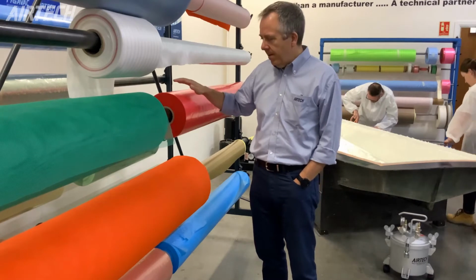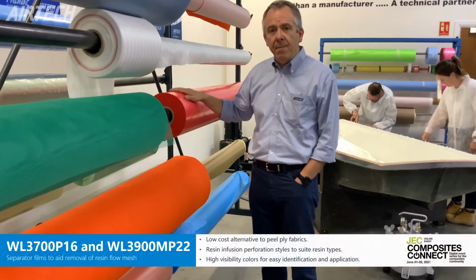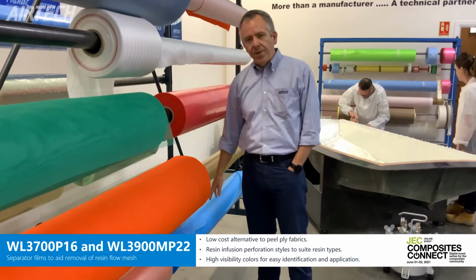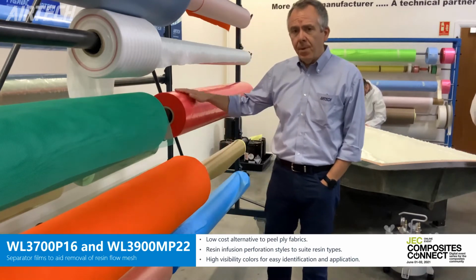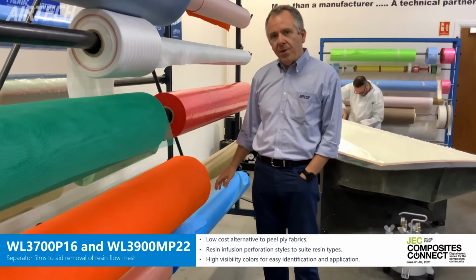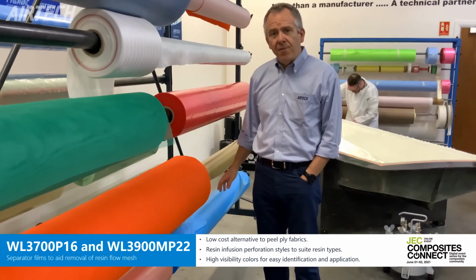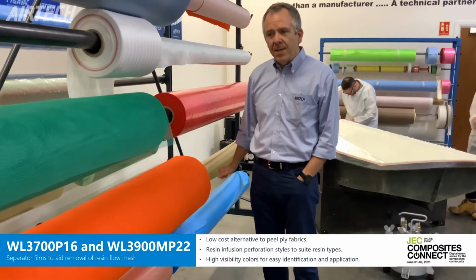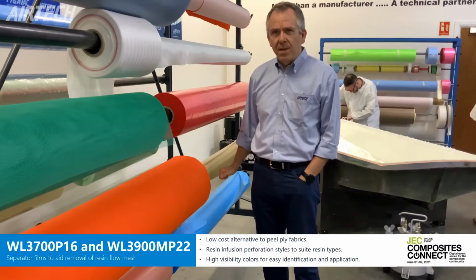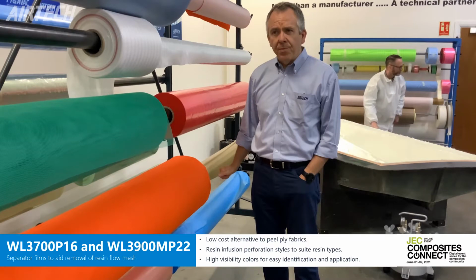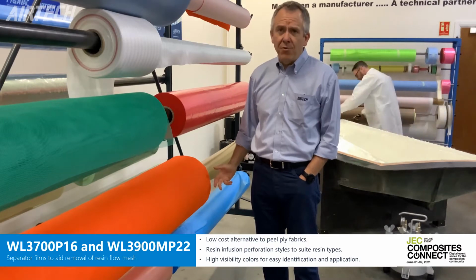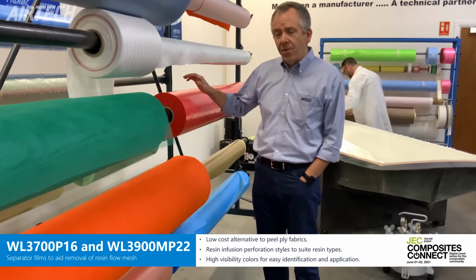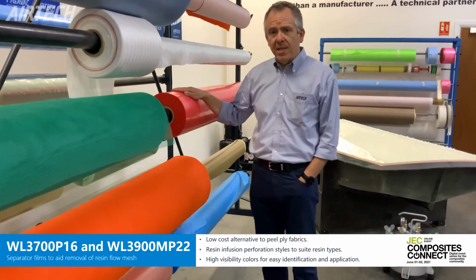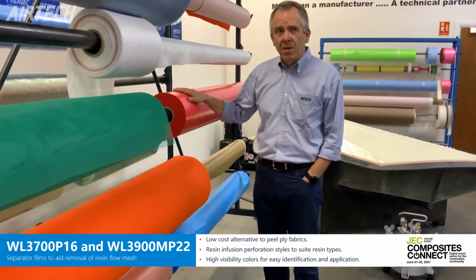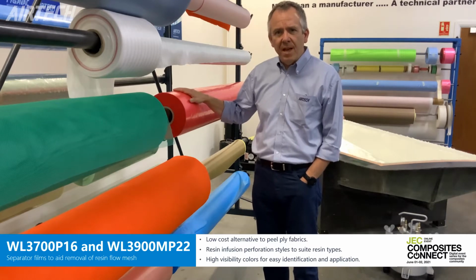So we have here WL3900 MP22 and WL3700P16. These are both polyolefins. WL3700 has about 500% elongation and a maximum use temperature of approximately 250 F, about 120 degrees C. WL3900 has about 500% elongation and a maximum use temperature of about 315 F, or about 155 degrees C.